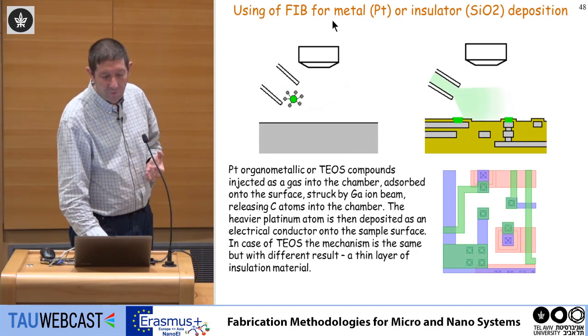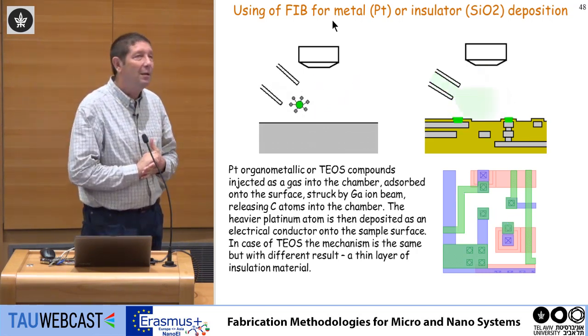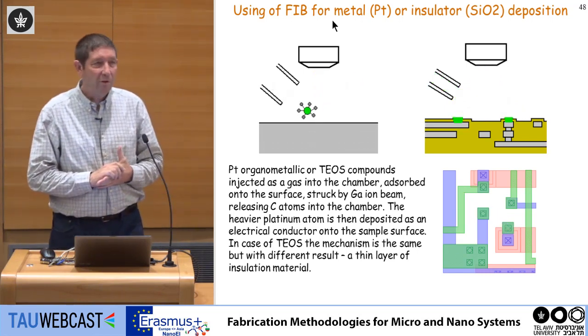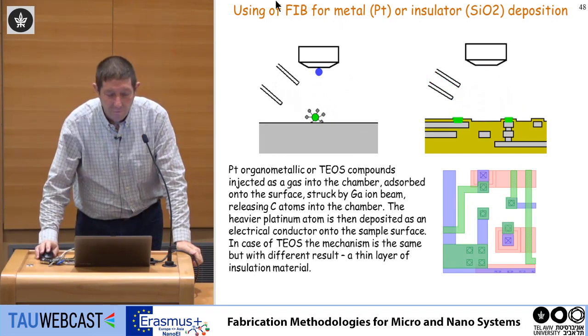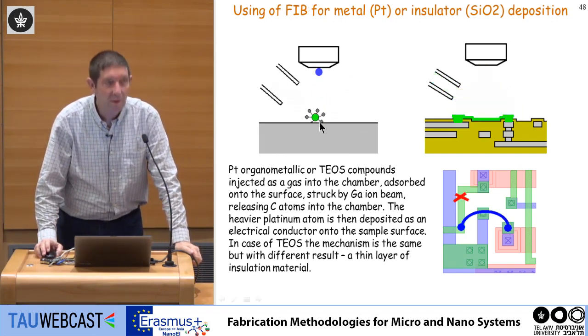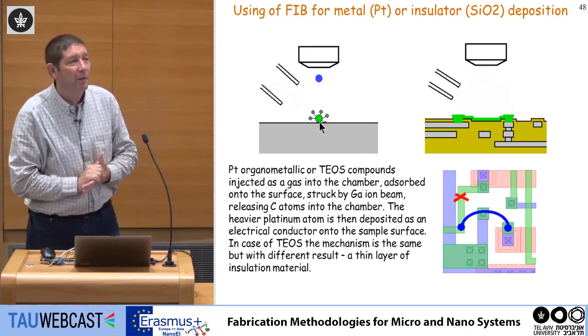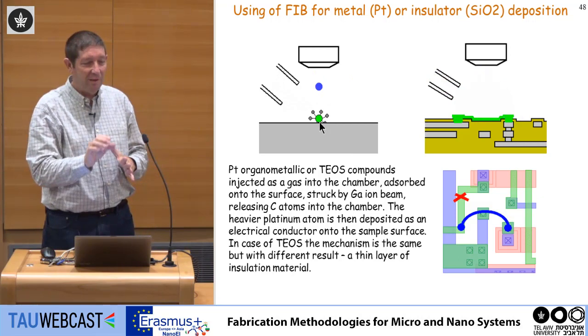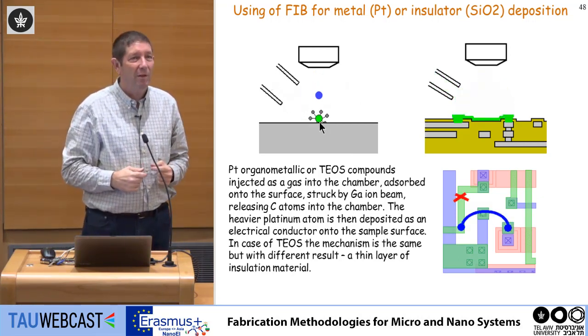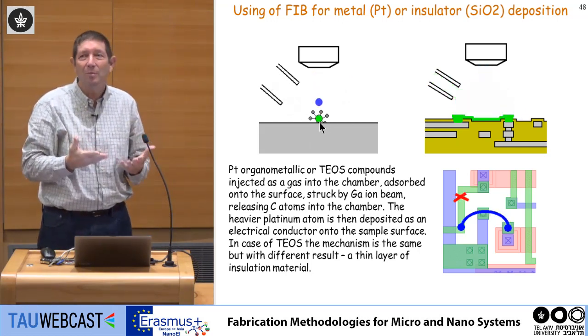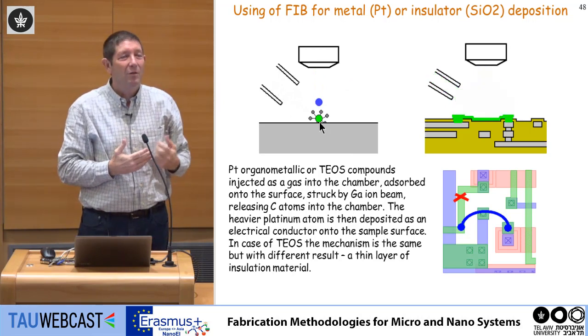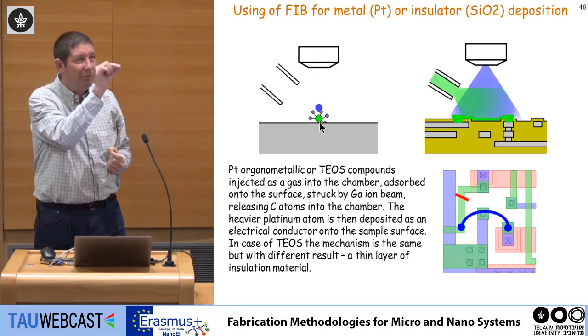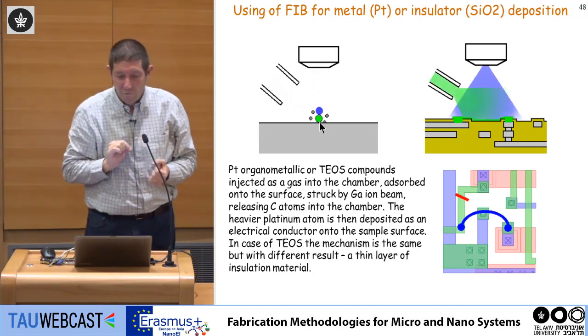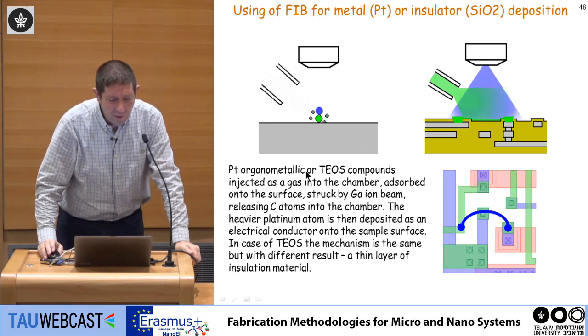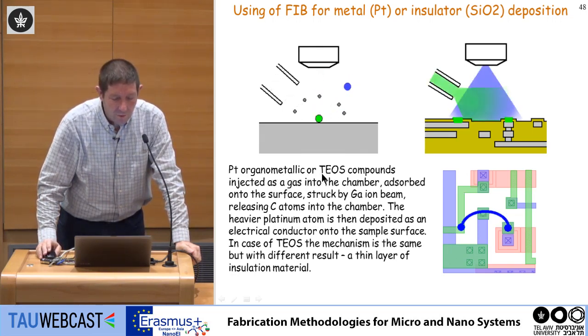For example, in another option, you can deposit metal. It's not so common, but people use it to deposit metal on insulator with very, very high resolution and where you want. Let's say you make a chip, and you look at the chip, and suddenly you see two lines are not connected. And you want to put metal connecting them. Now, you cannot do it post factum because the chip already finished the process. So what you do is, using this technique, you can deposit a very fine, very small line of platinum on the insulator.